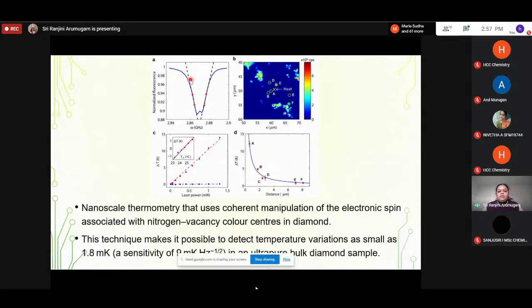So going into detail on the experiments, what you see is the 2.87 gigahertz NV center frequency, which is optically detected. With each point, the laser power has been varied, and the temperature is calibrated. So this uses coherent manipulation of electronic spins associated with nitrogen vacancy color centers in diamonds. This technique makes it possible to detect temperature variation as small as 1.8 millikelvin. So it's a very sensitive measurement,